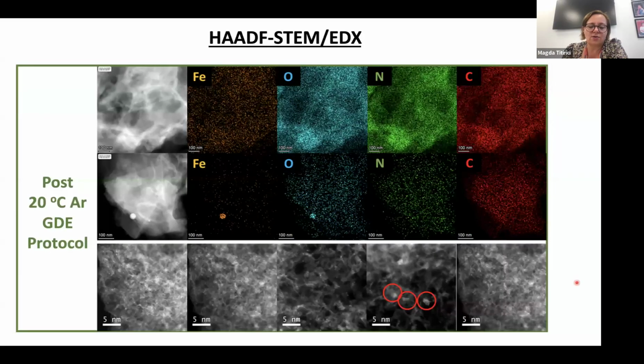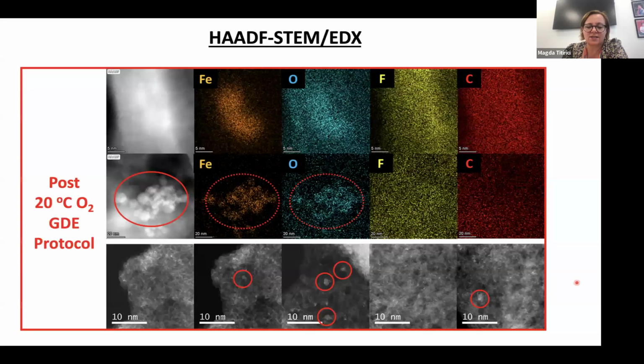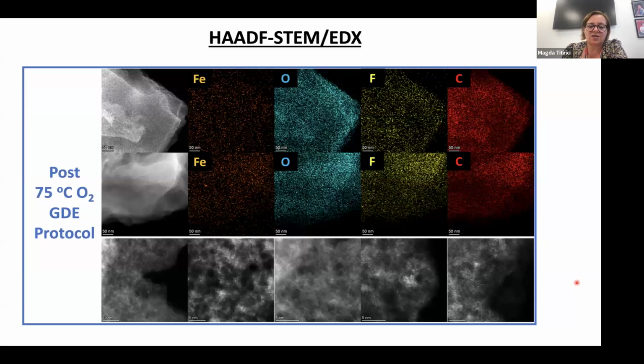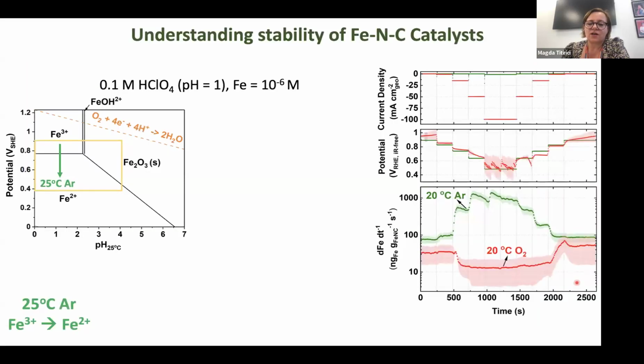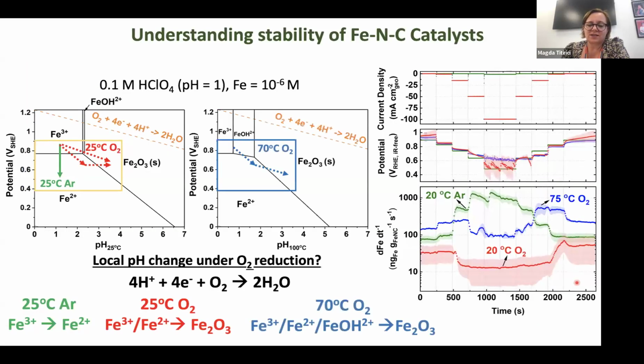And this is in argon where you still have nice single sites, but then in oxygen at 20 degrees, you start seeing these big aggregates, which means that your catalyst dissolves in the solution and reprecipitates. And strangely, at 70 degrees, you don't see aggregation, but you see quite a lot of loss in performance. So this is a very complicated thing.